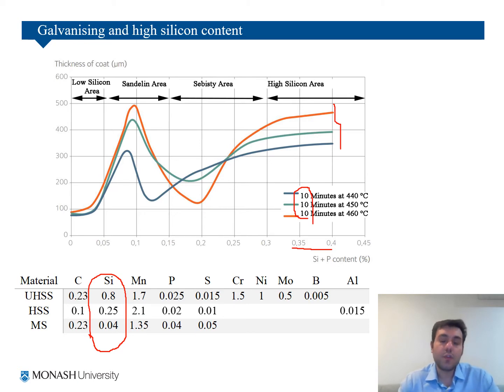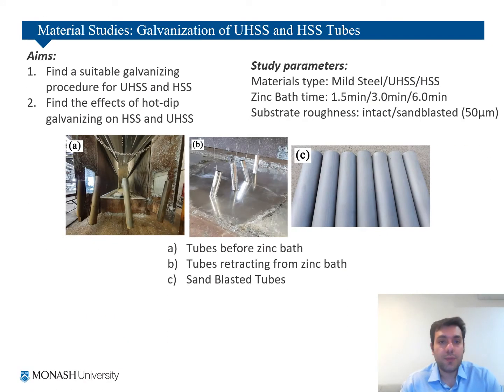So the aim of my study was to find a technique for galvanizing these types of tubes. So what we did, we took some tubes, mild steel, high strength steel, and ultra high strength steel, as you can see here. Then we galvanized them having intact surface or sandblasted surface. Why did we sandblast the surface? We wanted to see if the rougher surface increases the interlock or shear connection between the coating and the steel substrate to work in our favor to form a robust coating. And then we changed the bath time to see how it's affecting the material properties and the coating.